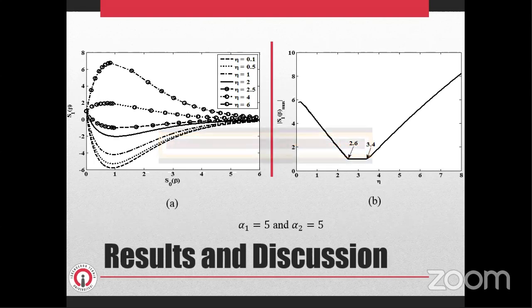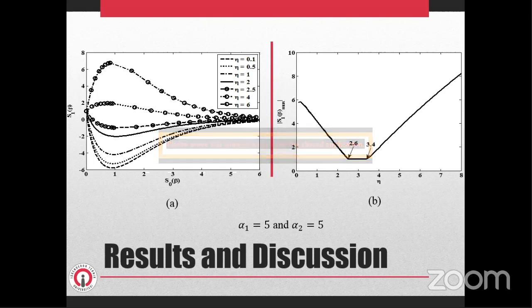And this Figure A shows the variation of S1 beta as a function of mean shell thickness at specific eta values when alpha 1 and alpha 2 are equal to 5. It can be seen that the effect of eta on the growth of the perturbation changes depending on its value. In the range of 0.5 less than eta less than 2.5, increasing eta causes a decrease in the growth perturbation amplitude. When eta becomes greater than 2.5, however, its effect turns out to be opposite, and increases the amplitude of periodic undulations at the moving interface.